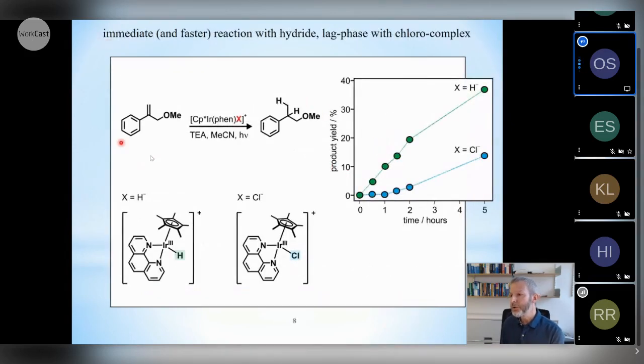Now this turned out to be a model reaction, this particular substrate, on which we discovered then that when we start from this iridium(III) chloro compound and we monitor the reaction progress as a function of irradiation time, not much happens in the first hour here, blue data points. It is only after approximately an hour that the reaction begins to set in and that this hydrogenation product is indeed formed.